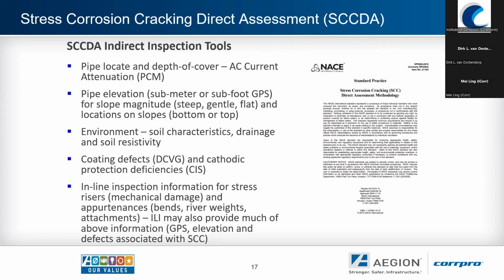This is important for the determination of the slope magnitude, whether we have a consistent or if there's any abrupt changes in the topography. Soil characteristics, so drainage, wetlands, and then soil characteristics as far as corrosivity become a big important factor to that. We also know that soil pH is a contributing factor in many cases to SCC. Coating defects usually are aligned and allow for collection of water, groundwater, that then undergoes some changes on the pipe surface. And then also cathodic protection deficiency. So marginal CP is also a known contributor to several forms of SCC.